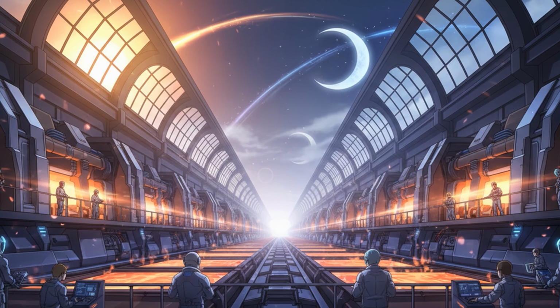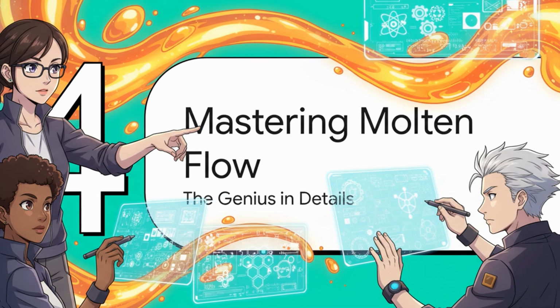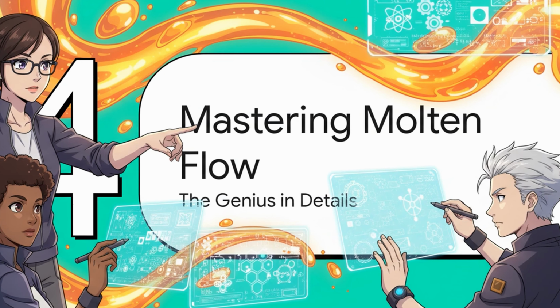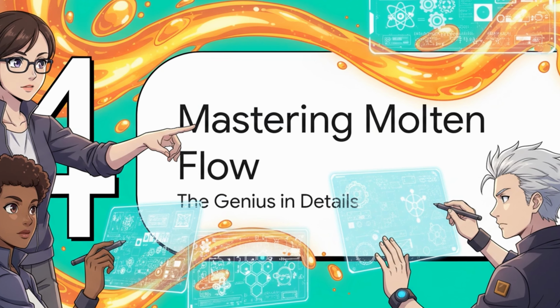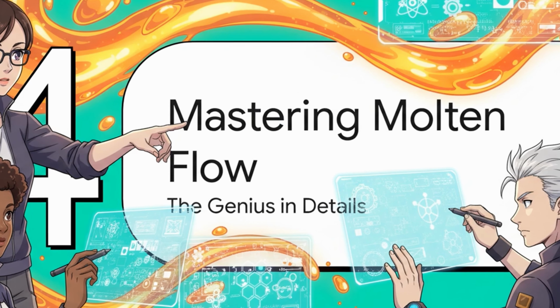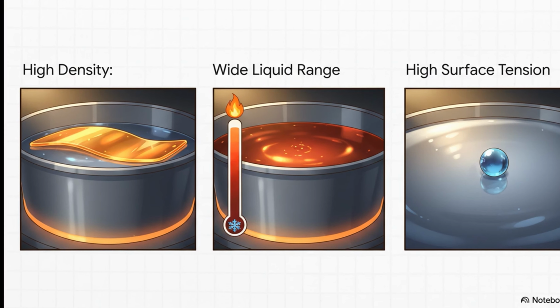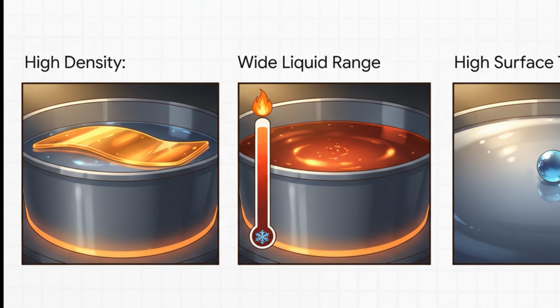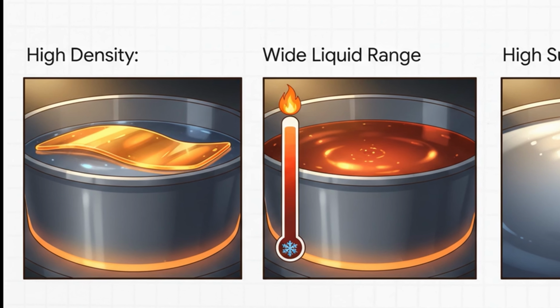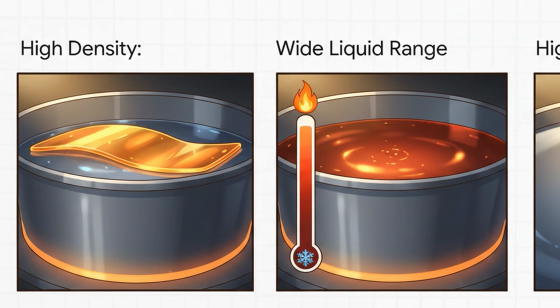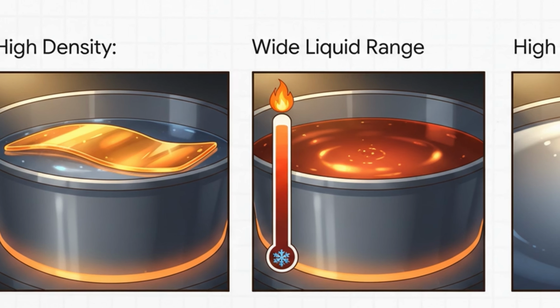Now, the big idea of floating glass on liquid sounds simple enough, but as they say, the devil is in the details. Making this process actually work perfectly meant solving some really fascinating and difficult physics and engineering challenges. So you might be wondering, why tin of all things? Well, tin is pretty much the perfect candidate for a few key reasons. 1, it's denser than glass, so the glass just floats right on top. 2, it stays liquid across the huge temperature range you need for this to work. And 3, and this is crucial, its surface tension is so high that it creates an almost perfectly flat, mirror-smooth surface for the glass to form on.